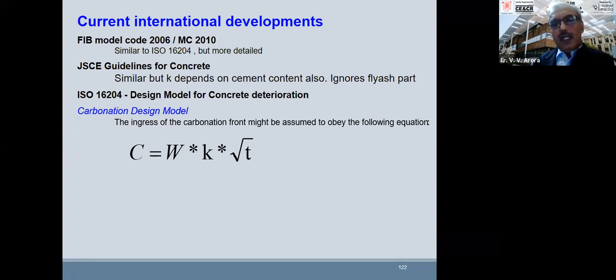So if the carbonation depth is less than the cover depth, the structure is safe. When the carbonation depth reaches the cover depth, then your service life is near completion. The corrosion will start occurring over there. You will have a few more years after that, but then it starts in a fast manner. So the only issue is how to determine how much time it will take to reach that. Once we determine that time, we have determined the service life in a way.